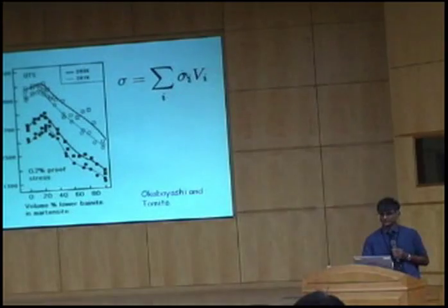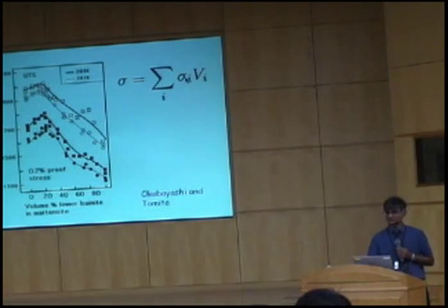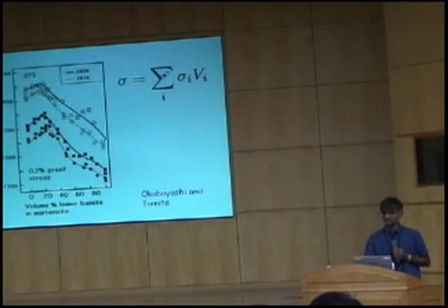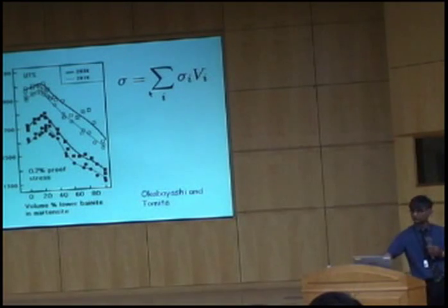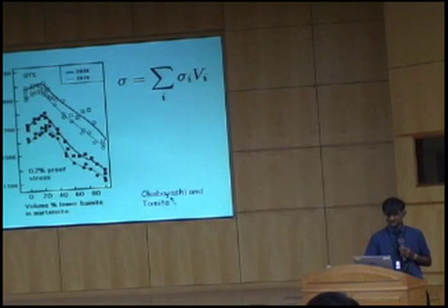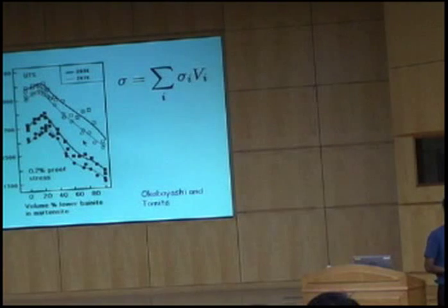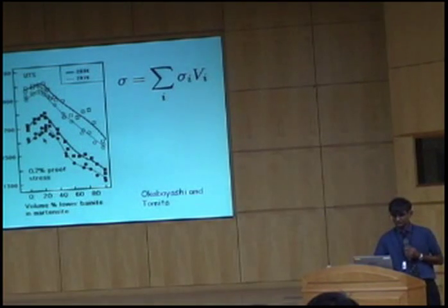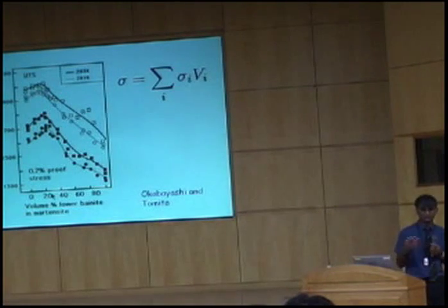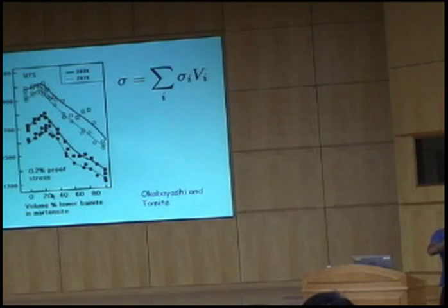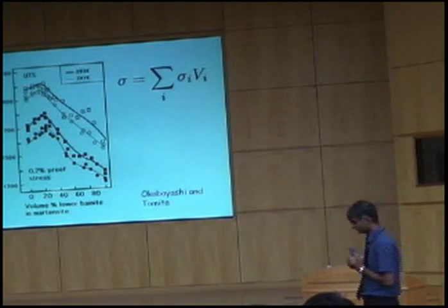So this is the normal way of dealing with mixed microstructures. So this, for example, is the strength of martensite and the volume fraction of martensite, and simply use an addition rule to work out the overall strength. And these are results published about 20 years ago, which show that that is not correct. Okay? For some reason, if you have a mixture of bainite and martensite, you actually get a higher strength at this fraction of bainite. So why is that? Why doesn't the strength simply go uniformly from 100% bainite to 100% martensite? What is it that is causing this peak in strength?